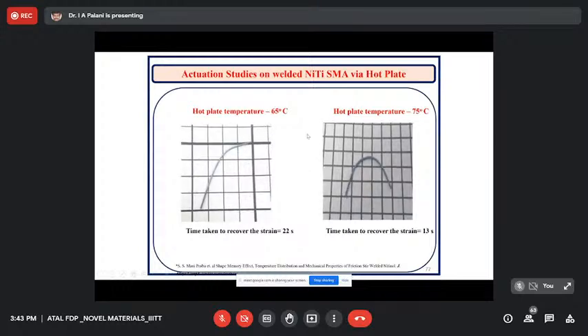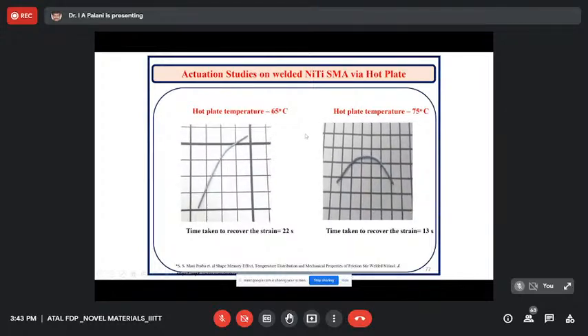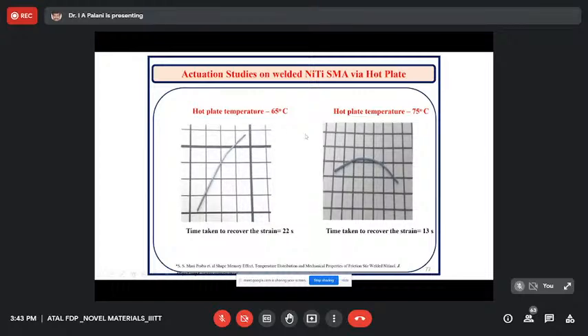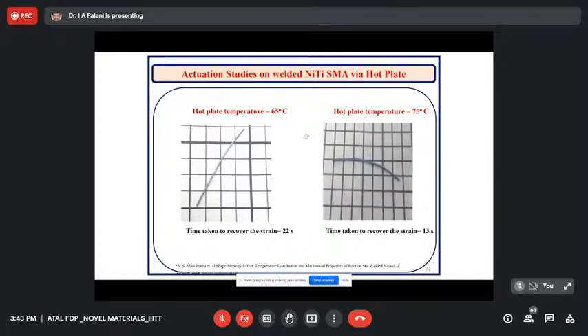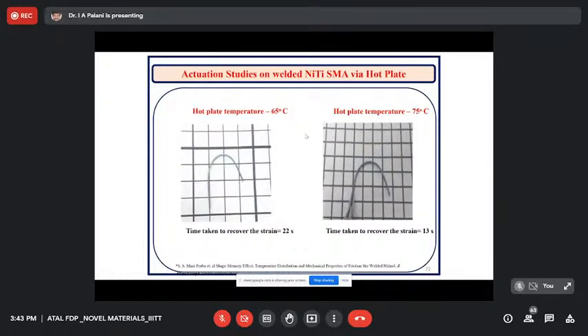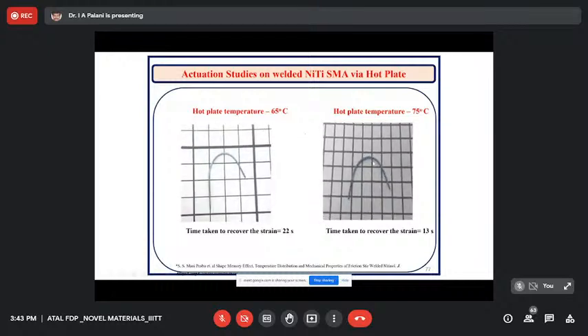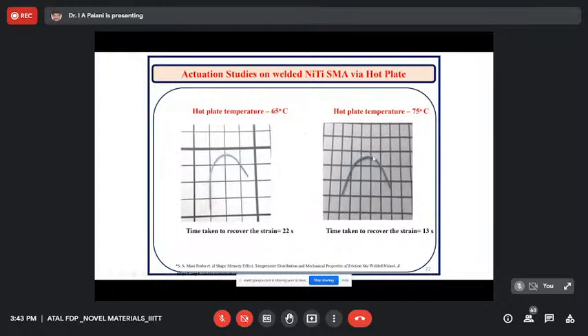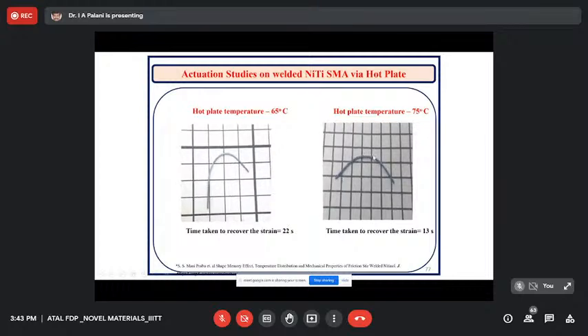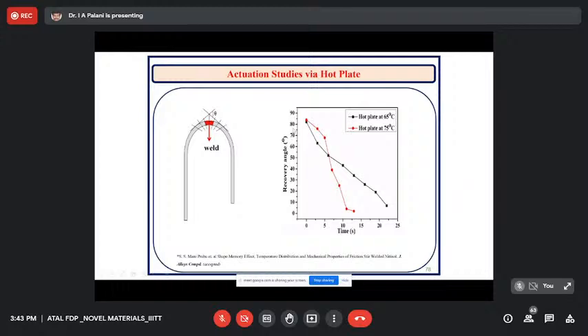In fact, at 65 degrees Celsius, the time taken to recover the strain is around 22 seconds, and at 75 degrees Celsius it is around 13 seconds. Okay, and here there is a weld joint which is not hampering your actuation. So this is an interesting part with respect to NiTi shape memory alloy.